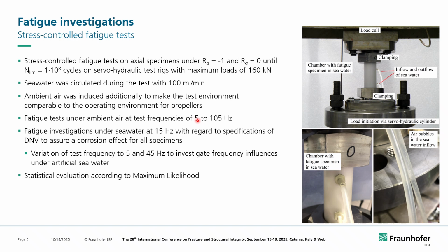But we were curious to see what is really the frequency influence. So beside the agreement with DNV, we made also some tests on the 5 hertz and 45 hertz, so a factor of 3 in both directions, to see what the artificial seawater can do in those times. Will we have a higher lifetime when we go to 5 hertz, or will we have a lower lifetime and fatigue strength when we go to 45 hertz? The statistical evaluation was done by maximum likelihood. That's our typical approach that we use.